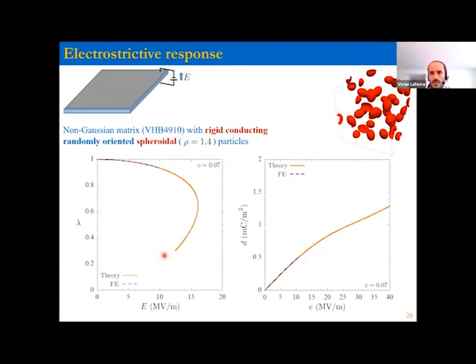As I mentioned earlier, it's valid for any isotropic microstructure away from percolation. I'm just showing an example here. You can see on the schematic that the particles are randomly oriented spheroidal particles. The aspect ratio is 1.4. Because they are randomly distributed and randomly oriented, the composite is isotropic. So we can use the formula.